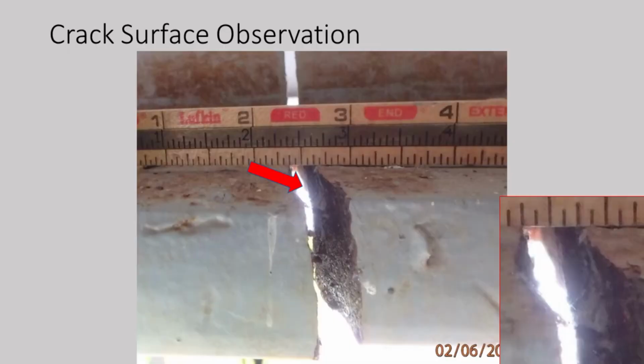And then we go back and start looking at their pictures. Fortunately, they took a few pictures, and we got to see a few things. And we look at this fracture surface here that's shown in this picture, which has the fortunate inclusion of a scale, a ruler, and we see something in here. And the rest of this is just a rough, grainy fracture, typical of what you think an unstable, brittle fracture looks like. But what's that in there?